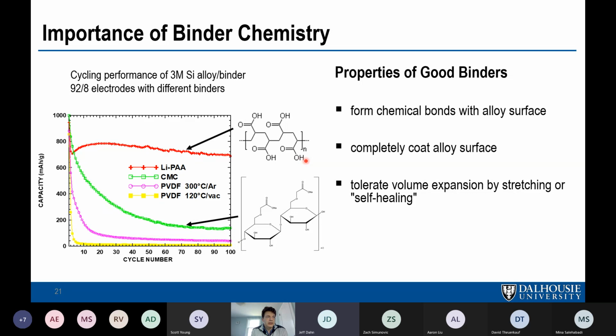So you're sintering the coating in the absence of air. So you're carbonizing the phenolic resin, right on the electrode support, right on the current collector? Put the electrode in a furnace. Yeah. Okay, then it'll cycle well.